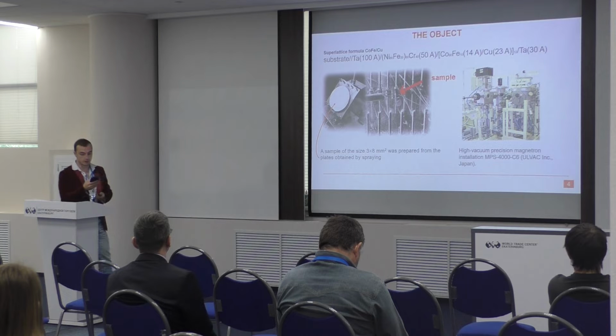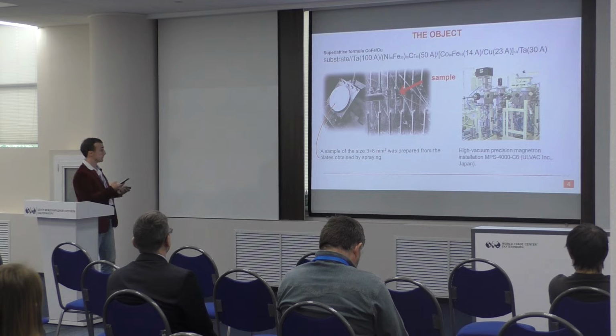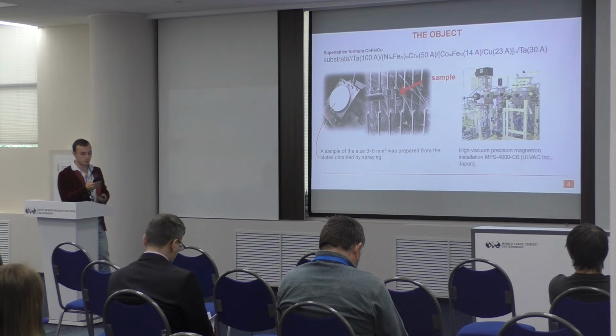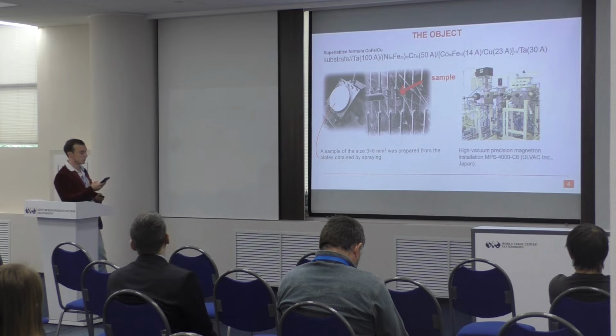For the studies, the plates you can see on the screen, cobalt iron copper superlattice samples with a size of 3 by 8 millimeters were prepared, which are necessary for measuring the magnetoresistance. The slide just shown has a sample fixed on a thin tungsten thread to exclude heat exchange with the surrounding objects.